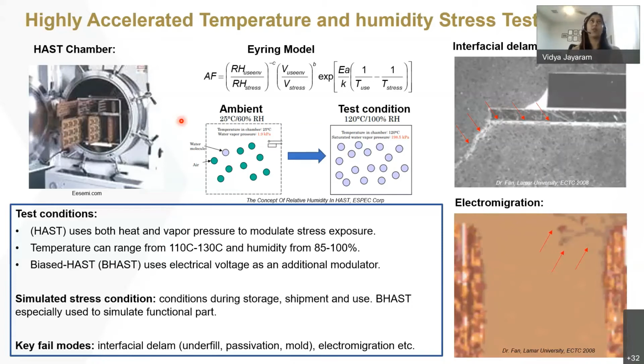But it's more of what kind of failure mode you're looking for and how that can be captured to pick between biased or unbiased HAST. So this typically will mimic your use condition or stress condition, where you have the parts being stored, shipped, or even in use, where you have areas with higher moisture, higher temperatures, etc., that would be able to simulate different kinds of fail modes like delamination and electromigration, etc.